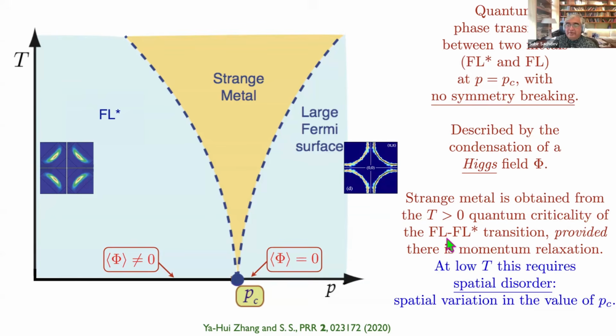So you have to put in momentum relaxations. And so we've been thinking about it a lot recently, and you could imagine what's called Umklapp processes, which are allowed in perfect crystals, but it's hard to see how they could be really important at low temperatures. So you have to really think about the effects of disorder on this rather exotic Higgs transition in a metal. And it turns out that the most important type of disorder, which one could have anticipated a long time ago, is what's called the Harris disorder. It's the fact that some regions of the sample are on the right of PC, the other regions on the left of PC, and you really have to take that into account in writing the theory.